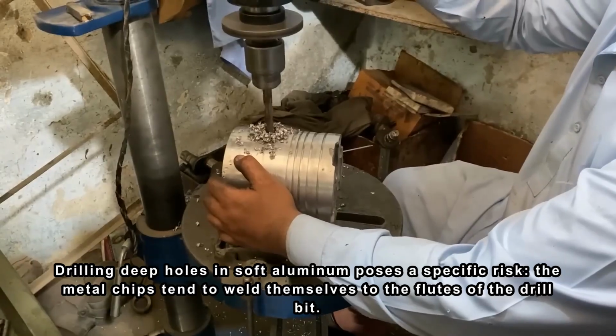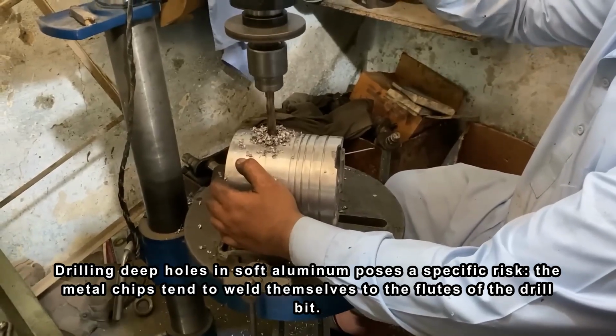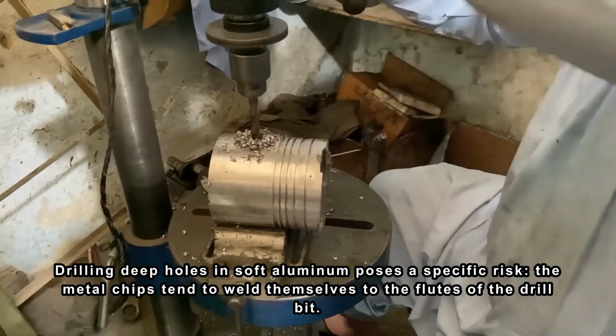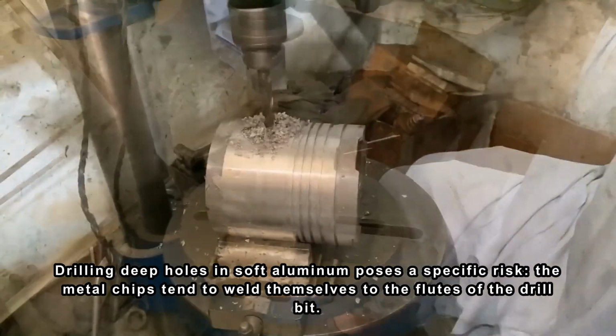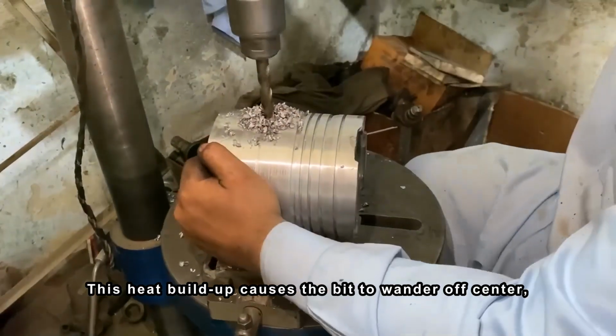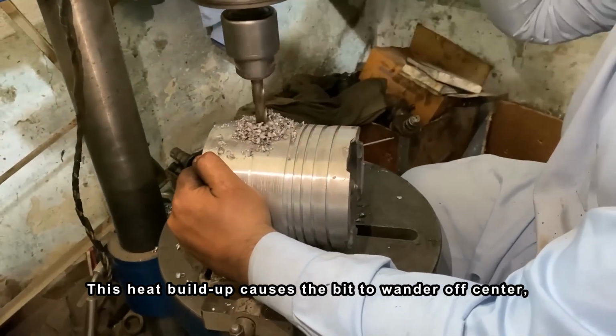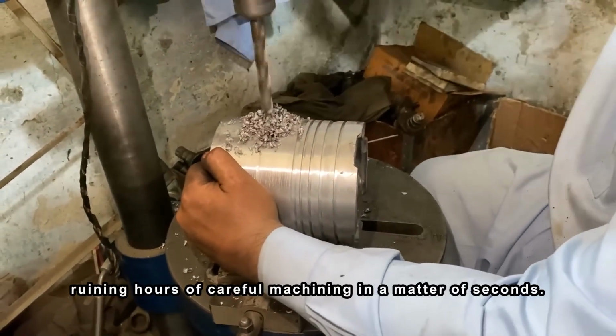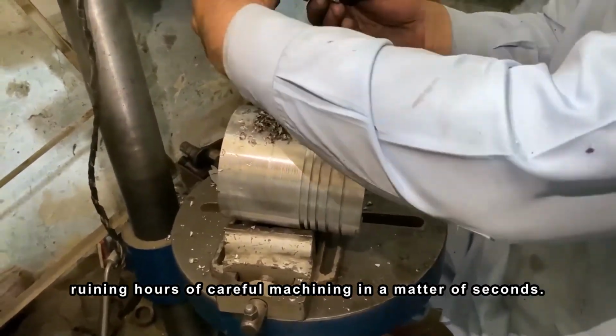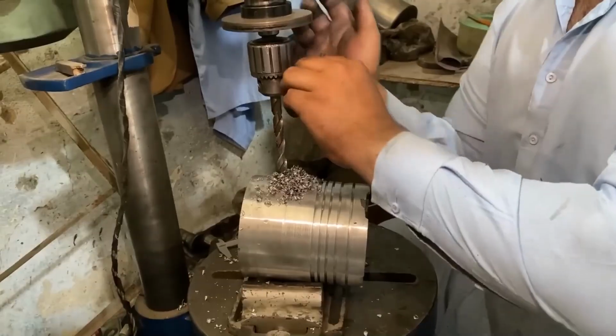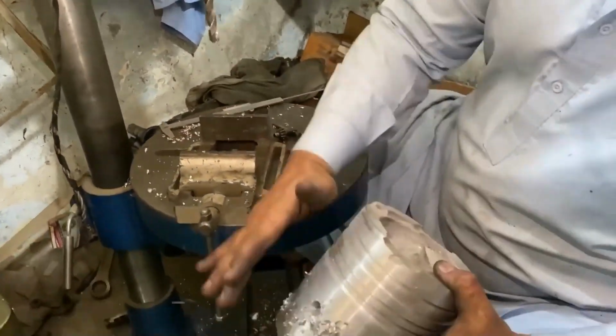Drilling deep holes in soft aluminum poses a specific risk. The metal chips tend to weld themselves to the flutes of the drill bit. This heat buildup causes the bit to wander off center, ruining hours of careful machining in a matter of seconds.